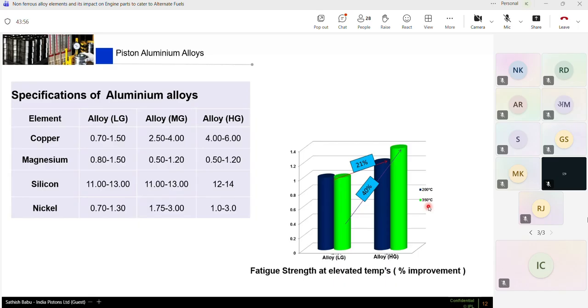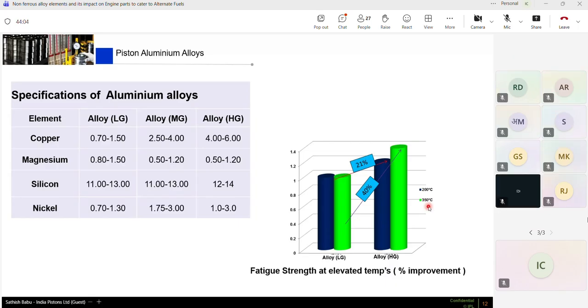Typically, with more amount of heat, obviously, the melting point becomes a concern for the aluminum alloy. The aluminum alloy melting point starts at almost 500 degrees, but the recommendation for maintaining the fatigue strength or the durability of the parts is strictly below 400 degrees centigrade. So there will not be any part allowed to run with more than 400 degrees on the piston with any kind of an alternate fuel. So we had a high grade alloy with a lot of elements getting improved, which gave a better fatigue strength at elevated temperatures.